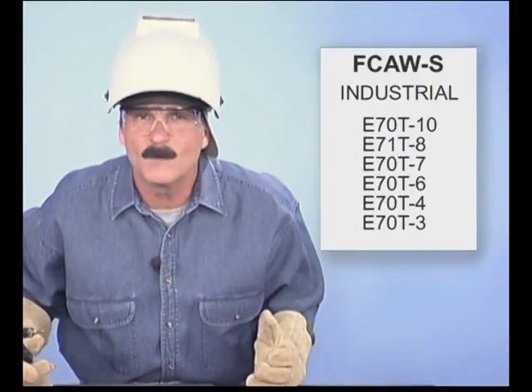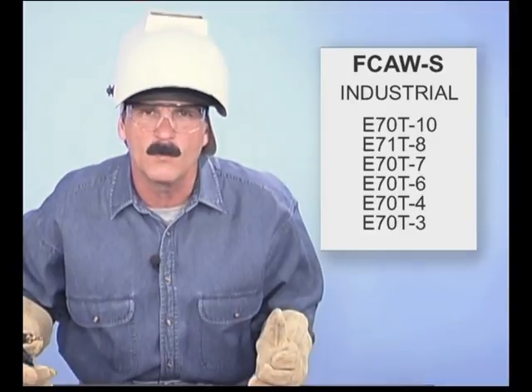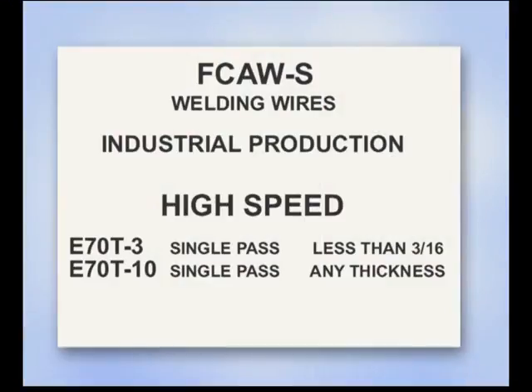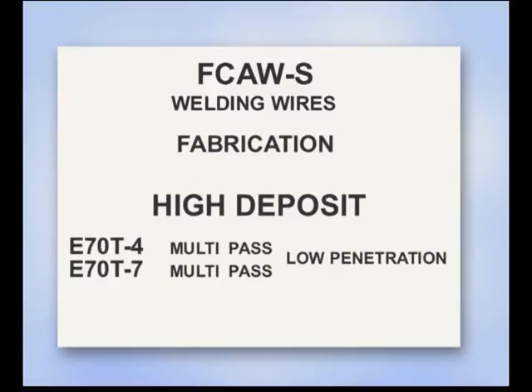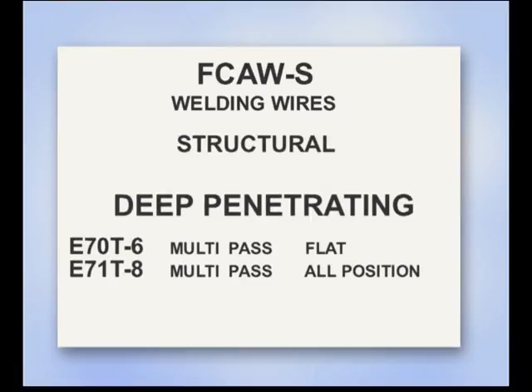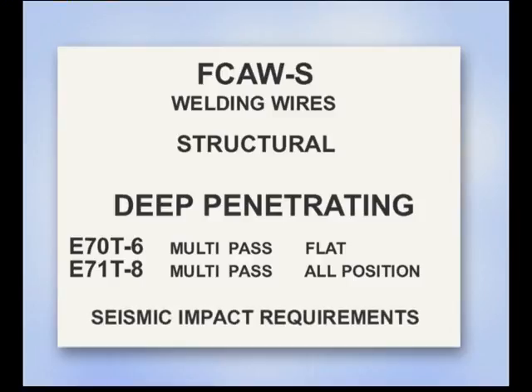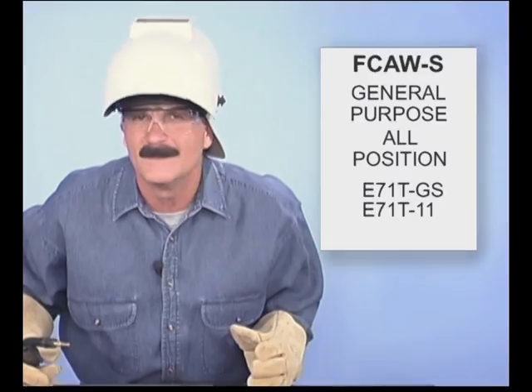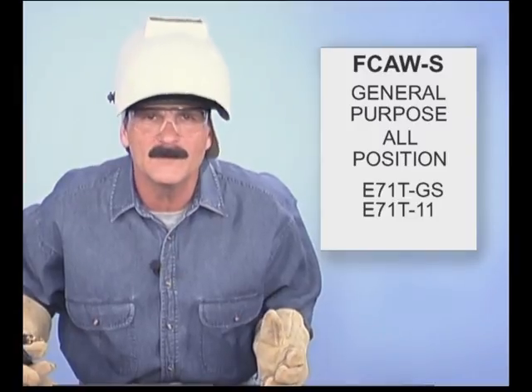Keep in mind, most wires were developed for industry, where welds are often made in the same position or specific mechanical properties are required. E70T3 and T10 are high-speed single-pass wires. E70T4 and T7 are multi-pass wires with high deposit rates. E70T6 and E71T8 are multi-pass, deep penetrating wires that meet the impact requirements for welding structural steel in seismic zones. For general purpose fabrication and repair in all positions,